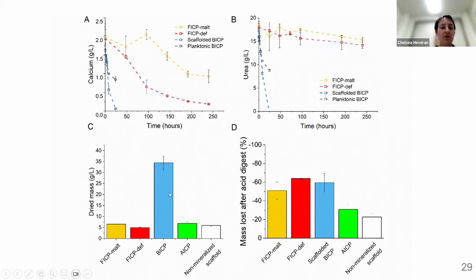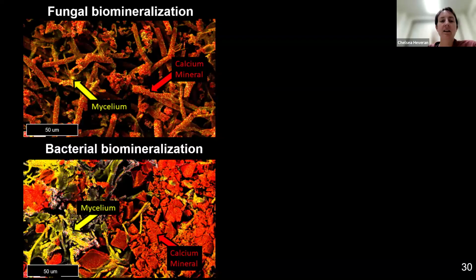When we then look at the dried mass, by far the highest dried mass is when we use the bacteria on a scaffold. As a percentage of how much mass we grow, it's actually similar between some of our fungus conditions and the bacteria conditions. It's just that we can build a way bigger scaffold first in the malt media, then kill it and mineralize it with bacteria, and that helps us build the fastest. So we saw that as an attractive way to move forward.